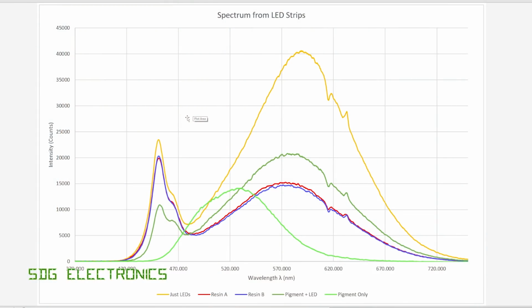So first of all, we have our output from our bare LEDs. Now, because these are blue LED dies with a phosphor coating, these all have a peak at about 450 nanometers. So that's the base output from the blue LED emitter. And then the phosphor is basically what dictates the color temperature. And because these are very warm white, there's a lot of phosphor in the 600 nanometer region that gives us this large peak over here. And that's what makes it appear very warm white. So this is exactly as we'd expect.